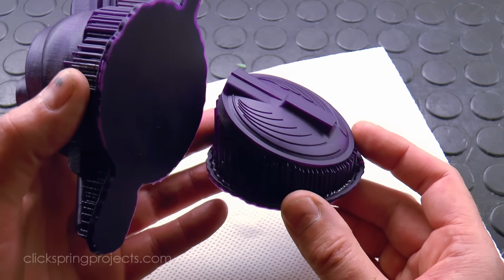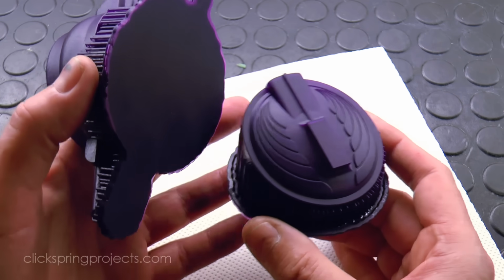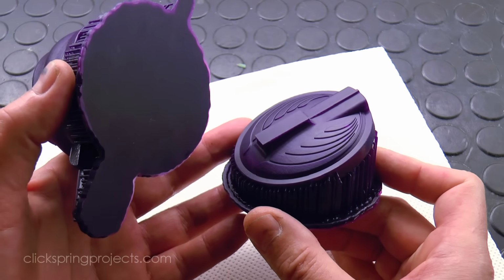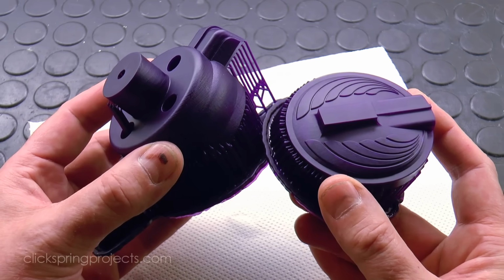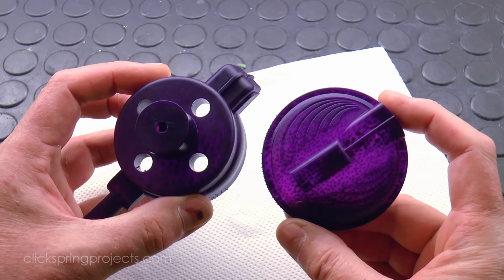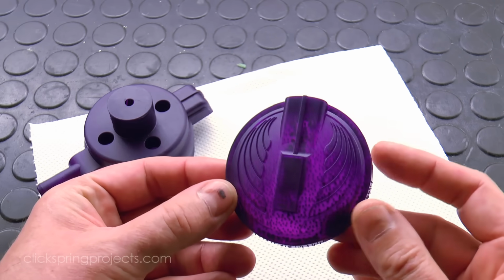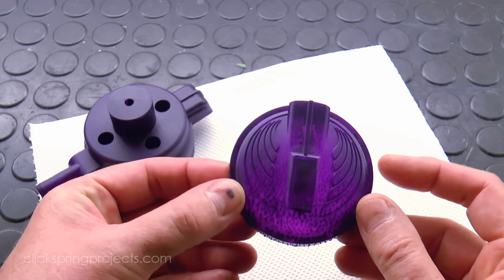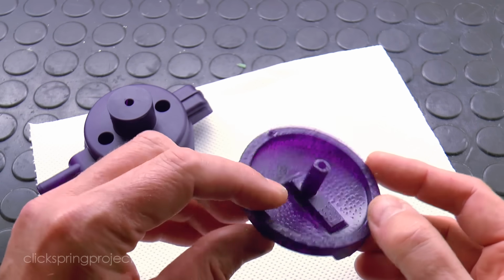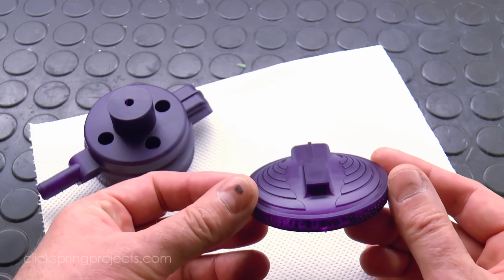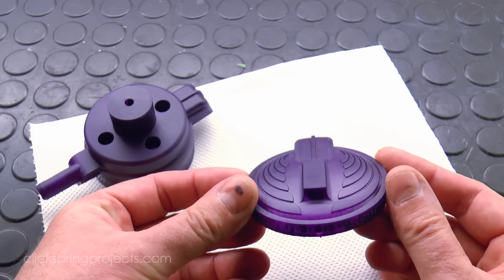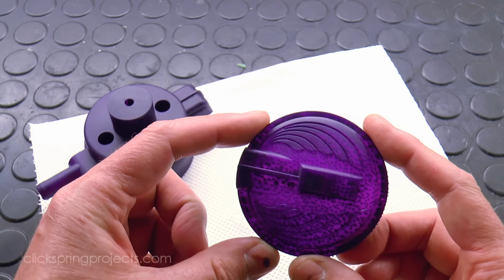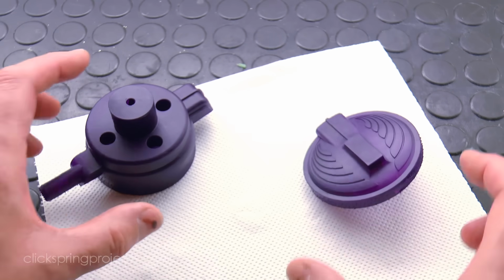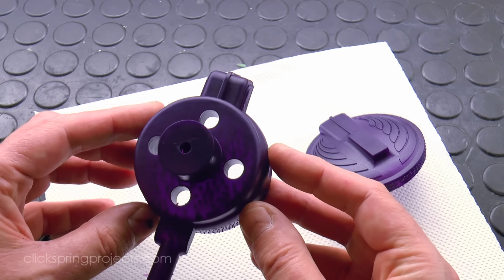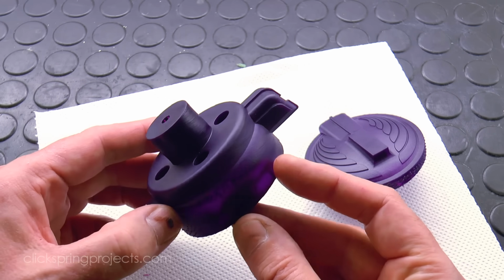I'm going to cast these prints in silicon bronze, and previous testing has indicated a suitable shrinkage allowance to be around 1.6%. Now, for all of the convenience of 3D printed patterns, there is one major drawback. The printed resin tends to expand slightly when heated, which can cause cracking of the mould, and occasionally the breaking off of delicate features. Simply choosing ceramic shell as the investment goes a long way to solving this issue, given its greater strength compared to gypsum investment.